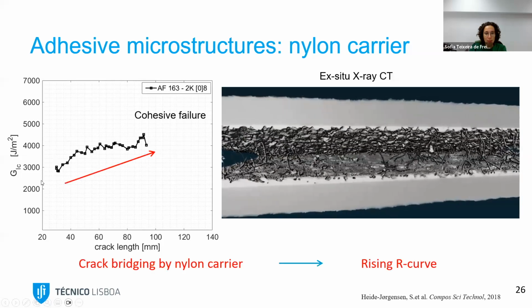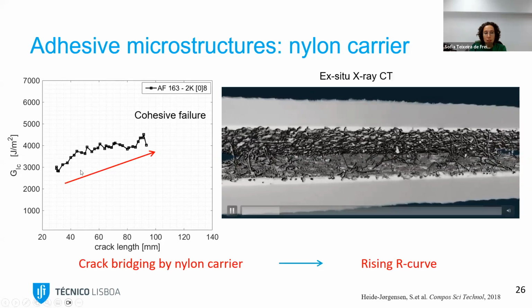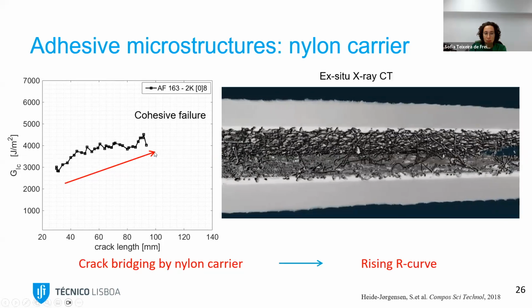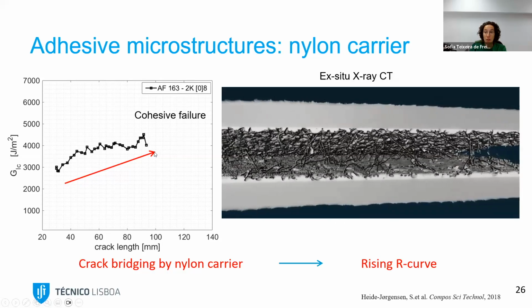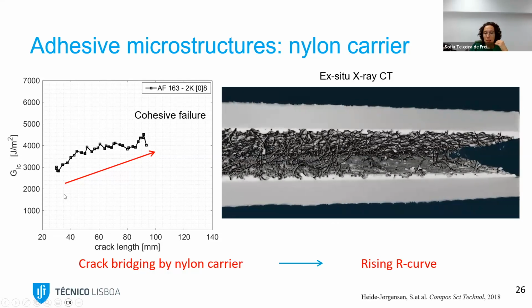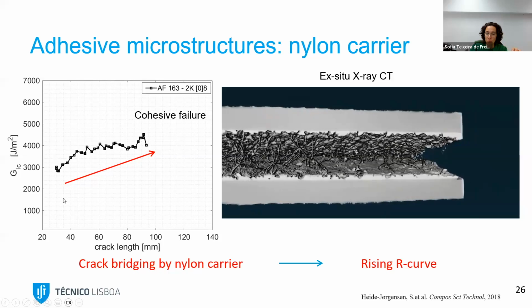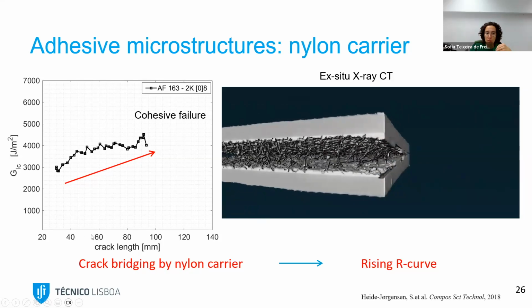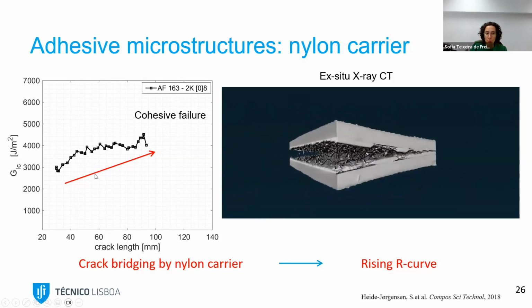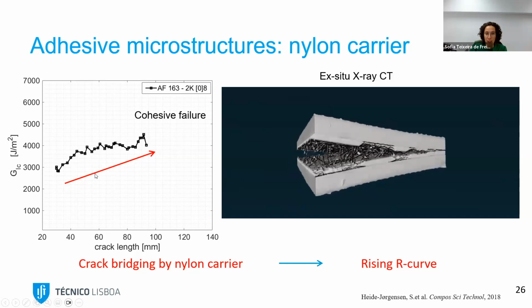what we see is that we have an increase in the fracture toughness, the energy release rate. And as you remember, this is exactly what we wanted with the fracture toughness, that every time we increase the crack, the energy necessary to increase further the crack is even greater.